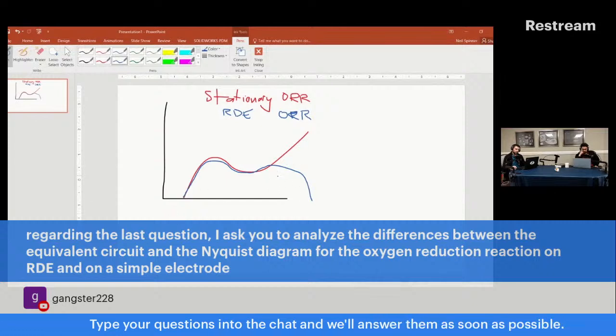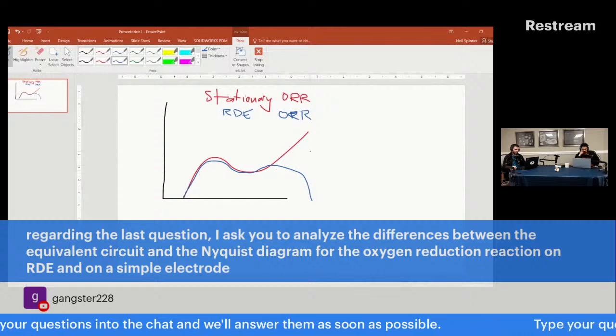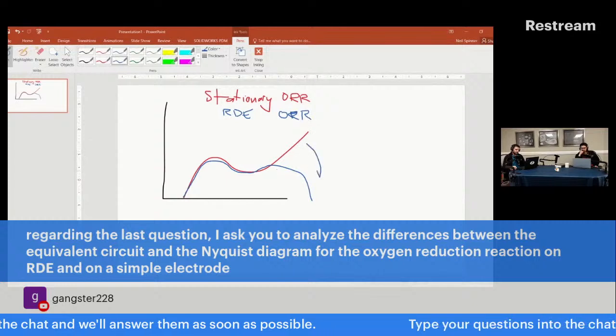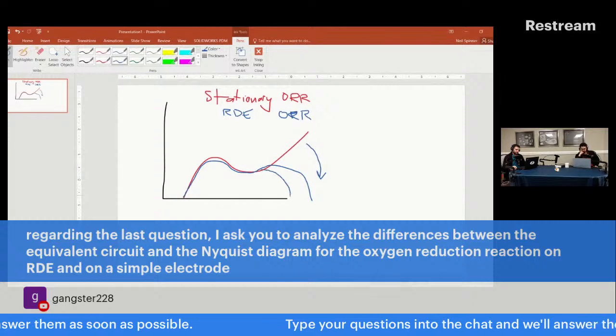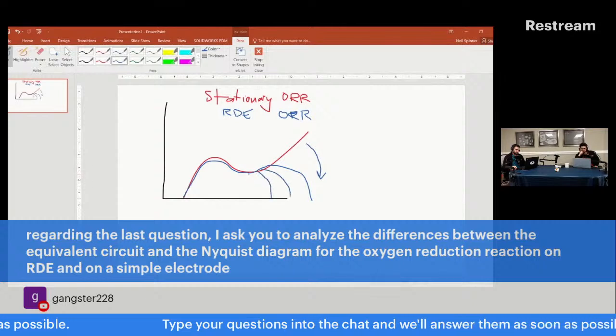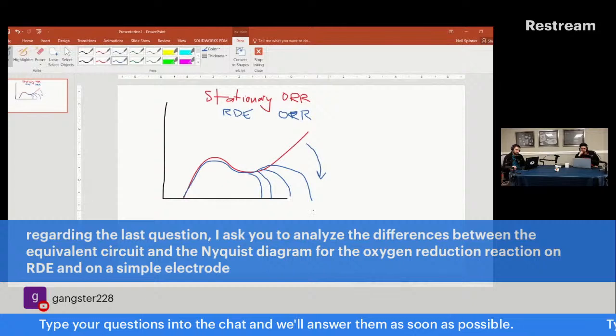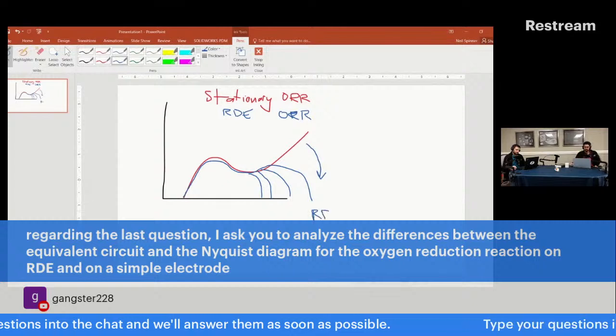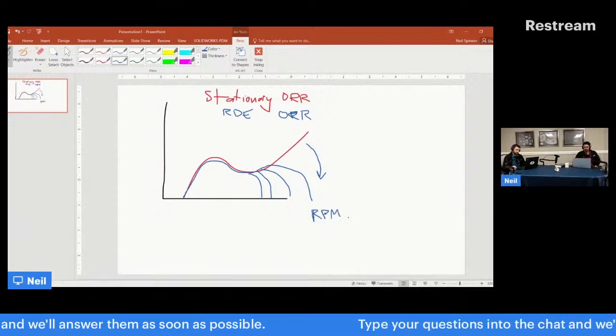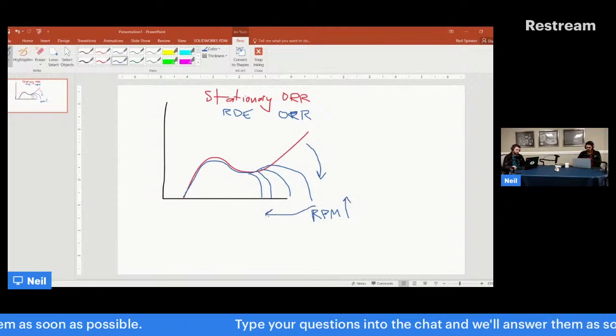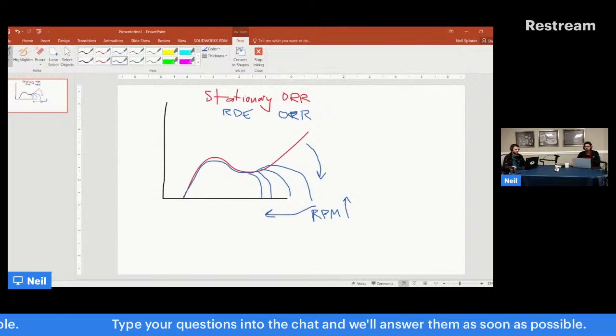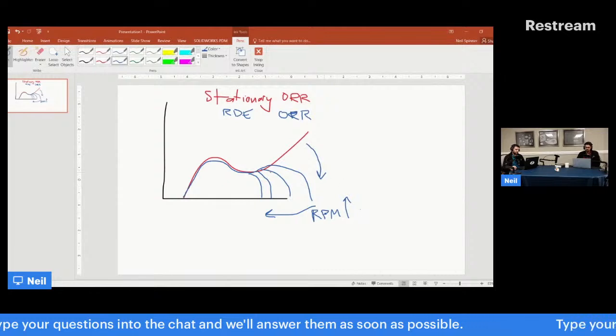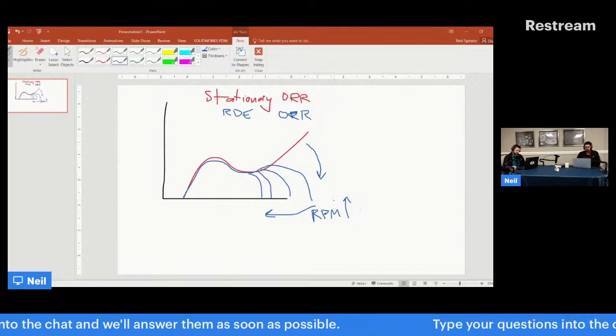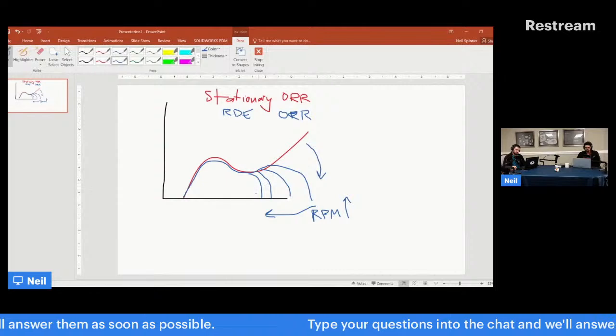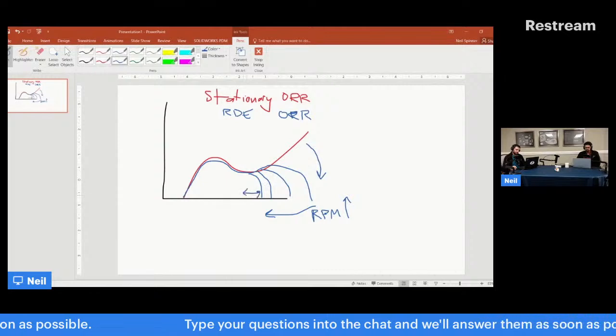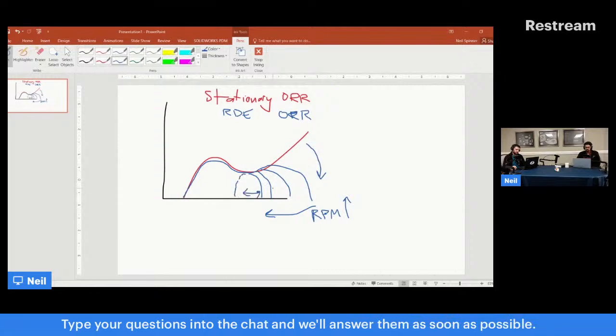You basically get a Warburg short. And you'll get this start to decrease in width, the semicircle, as RPM increases. It goes this way. There's like 1,000 arrows here. Sorry. As RPM goes up, this red curls down and then gets the semicircle to shrink in width. If this is a width, you could think of this like a width of a semicircle, sort of.